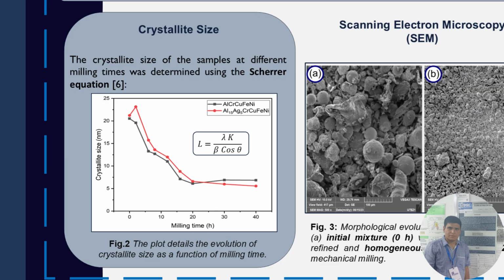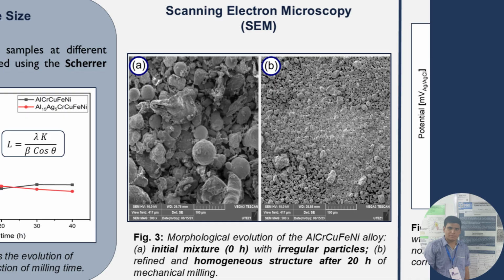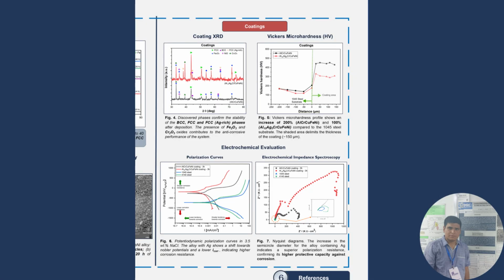This refinement is mathematically supported by the crystal size evolution plot, calculated via the Scherrer equation. The crystal size drops drastically during the early stages of milling and stabilizes below 6 nanometers at 40 hours. Furthermore, scanning electron microscopy images in Figure 3 visually confirm this morphological evolution. We transition from the initially irregular, coarse elemental powder mixture at 0 hours into a highly homogeneous and refined particle structure after mechanical alloying. Now let us discuss the performance of these materials when applied as coatings.